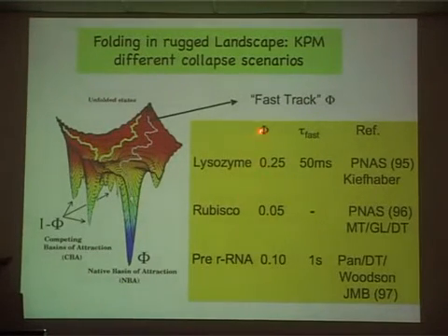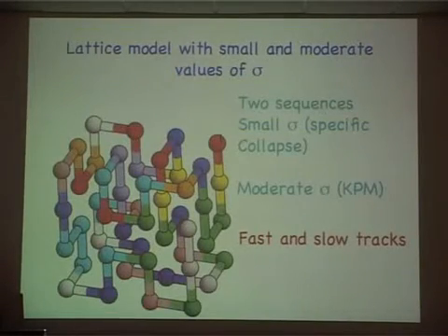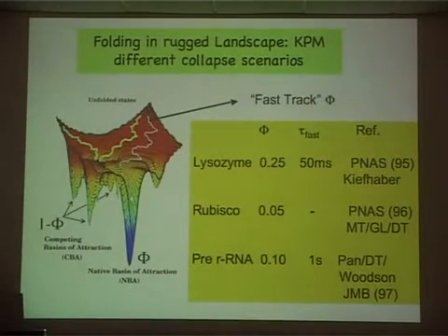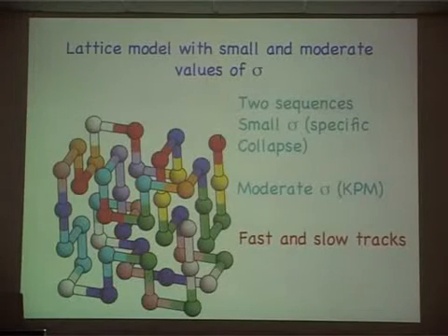And the values of phi, the fraction of molecules that fall directly to the native basin of attraction, range from about 5% to about 25% for these systems. They can even be smaller. Parenthetically, I note that for systems in which this phi is extremely small, these are called non-permissive conditions. And for those proteins, it is suspected you need chaperones to actually assist them to fold before they start to aggregate. So these are in vitro, right? All these are in vitro experiments.